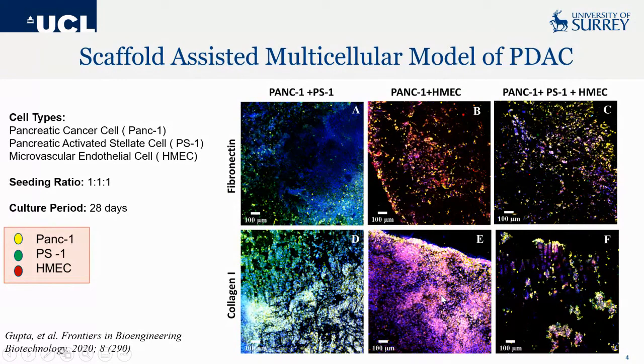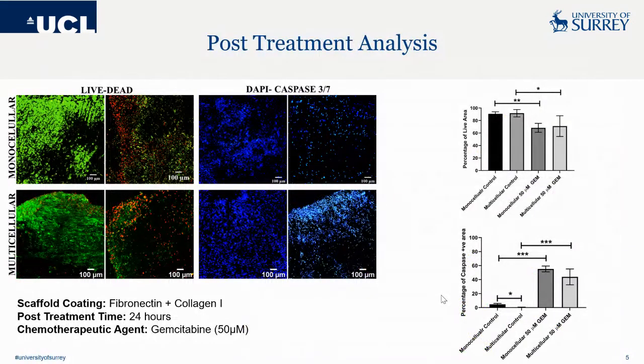So what we concluded from this particular system is that we need a system where we have cancer cells for the pancreatic, we need fibronectin coating for the cancer cells, and we need collagen coating for the stromal cells, which are the endothelial cells and the stellate cells. So we went ahead and did a cocktail of fibronectin and collagen 1 coating. We coated the scaffolds and we put our cells on them, followed by 4 weeks of culture.